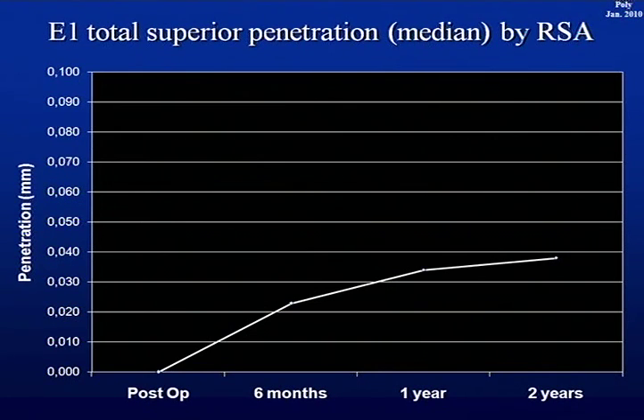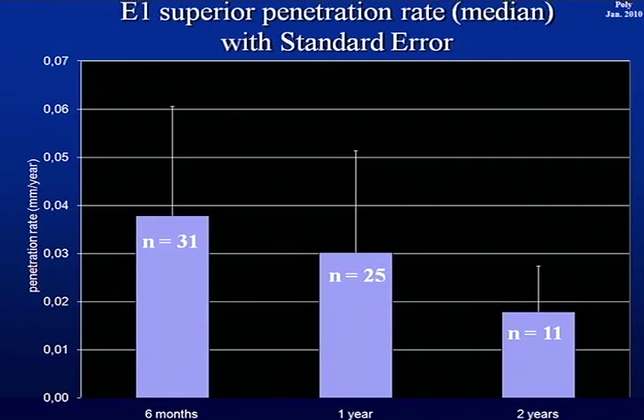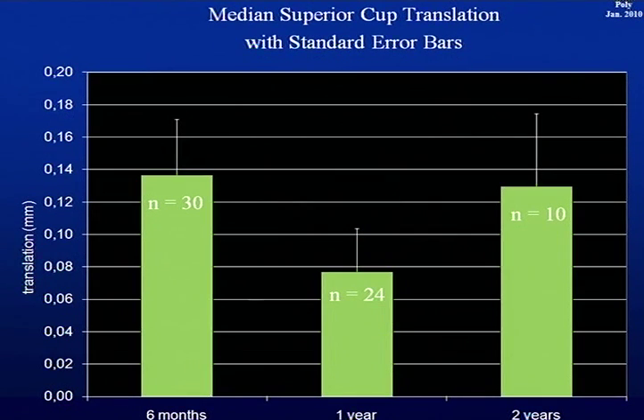This is the total superior penetration of the head into the poly. This is 10 micron, 20 micron, 30 micron, 40 micron. Up to 2 years, the total penetration is less than 40 microns, which is less than we have seen before. We should expect less deformation of the material because there's a higher crystallinity. And this is the rate, the speed with which the head is moving in, initially high, deformation up to 40 micron, and then decreasing with increasing follow-up. Of course, these are preliminary results, but as for longevity, it looks as if no unexpected events will happen.